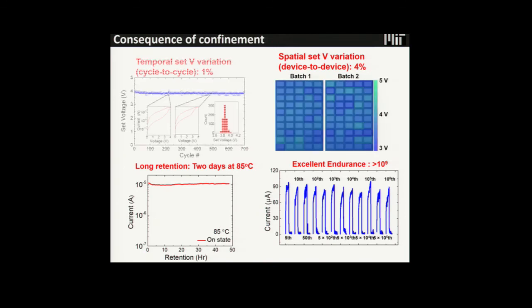Okay, so what is the consequence of the confinement? Of course, you have very uniform device performance and long retention. Long retention means once a silver ion goes into the dislocation cage, it's just locked up there, so it doesn't go anywhere. That means long retention. As the metallurgy concept says, it works for the memristor device. You can see retention is really long and endurance is high.